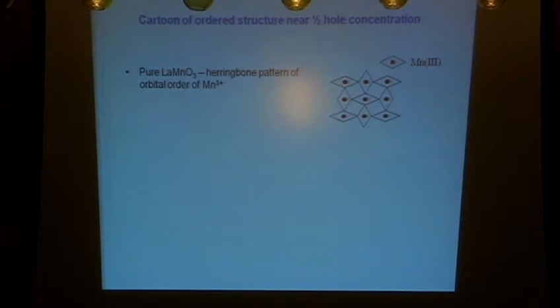And let me begin with a sort of a cartoon of the structures to explain how it's natural to think about them. If you begin with lanthanum manganate, that is manganese 3 plus. Manganese 3 plus has one electron sitting in an eg orbital, which can typically point out this way or that way, the way that I drew it. And when it points in a particular direction, it moves the oxygens, which are at the edge of the octahedron. This is a slice through a perovskite structure. And so if the orbital's occupied this way, and then this way, and then that way, you get this kind of herringbone pattern, which in fact describes quite well the structure of lanthanum manganese oxide, and was understood as such in the 50s.